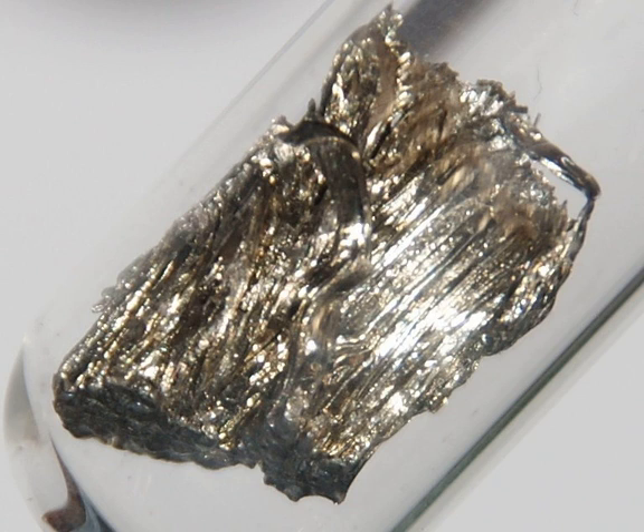The diiodide can also be prepared by heating SmI3, or by reacting the metal with 1,2-diiodoethane in anhydrous tetrahydrofuran at room temperature: Sm(s) + ICH2CH2I → SmI2 + CH2=CH2. In addition to dihalides, the reduction also produces numerous non-stoichiometric samarium halides with a well-defined crystal structure, such as Sm3F7, Sm14F33, Sm27F64, Sm11Br24, Sm5Br11, and Sm6Br13.